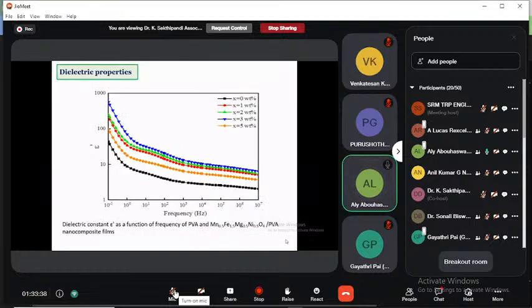This improvement and the increase in the refractive index is due to the filler nanoparticles increasing the packing density of the film, the number of atoms per unit volume, which also increases the scattering effect and slows down the light speed in nanoparticle films. In addition, we also measured the dielectric properties of this material.